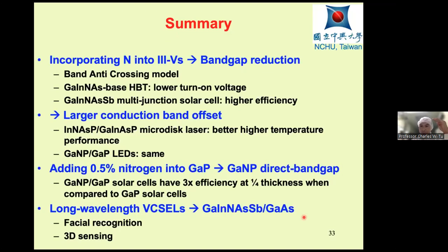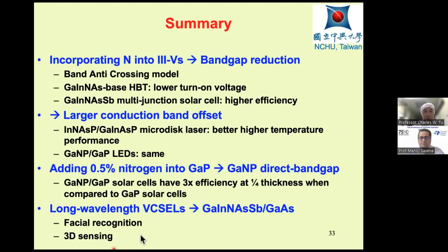The reason for bandgap reduction in incorporating nitrogen can be explained by this band anti-crossing model, and then we have advantages due to lower bandgap, or larger conduction band offset, and change of band structure from indirect to direct. And so all this has advantages. But I also mentioned the challenge of these point defects, dangling bonds. But now there is a renewed interest in this long wavelength VCSEL for facial recognition and 3D sensing.